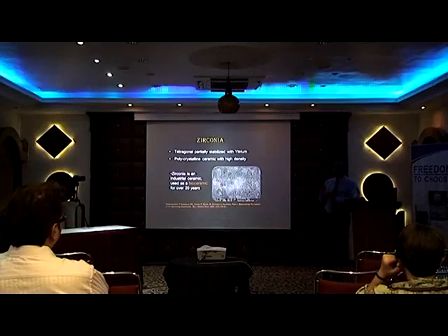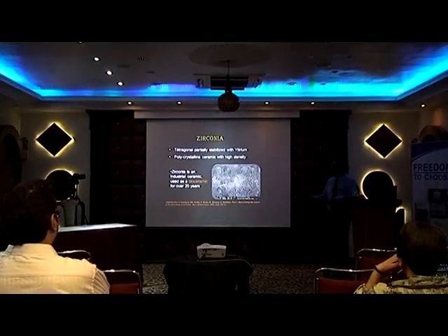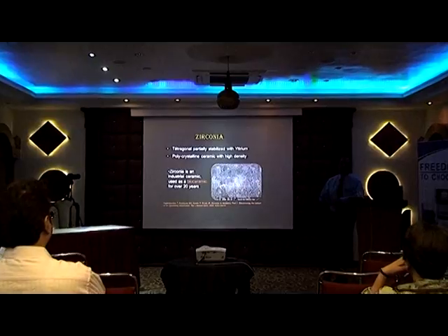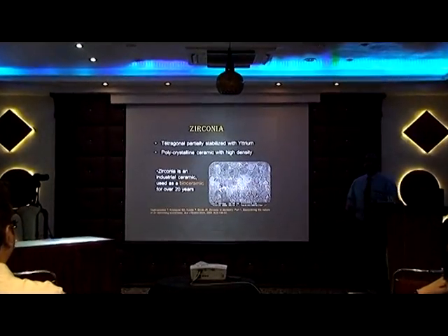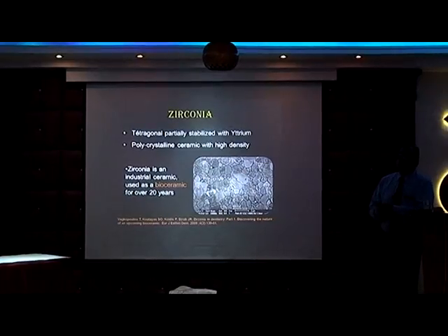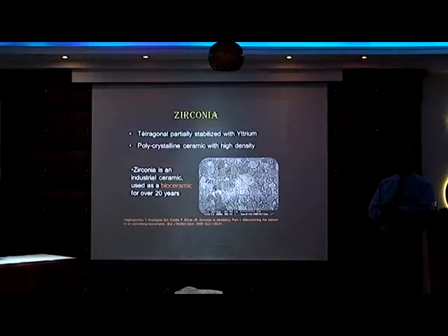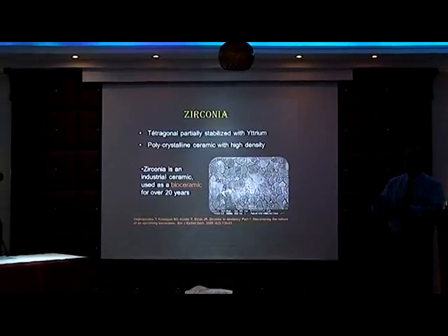Just limited to that, there's a 4% increase. This volumetric expansion causes a crumbling of the whole structure in the monoclinic phase. We don't want that, because monoclinic is what it is going to be at room temperature, but we want to maintain the tetragonal phase properties. So we stabilize it with yttrium, 3 to 5% yttrium, cerium, etc.